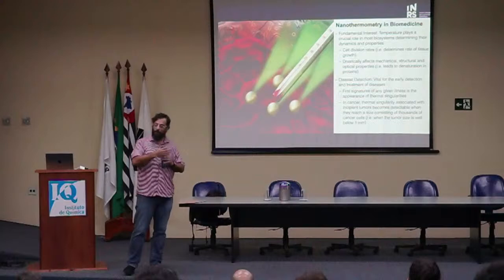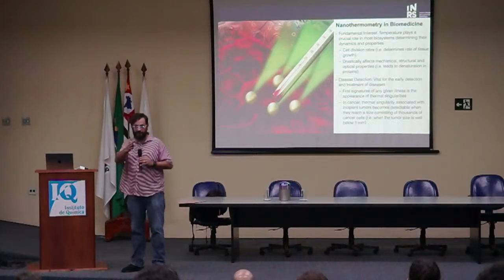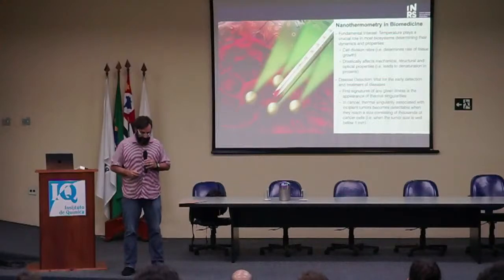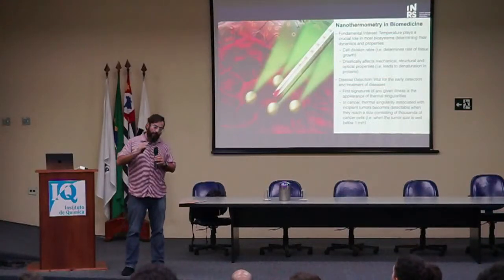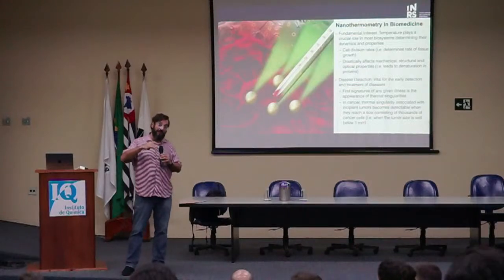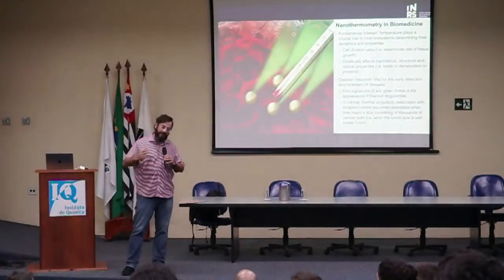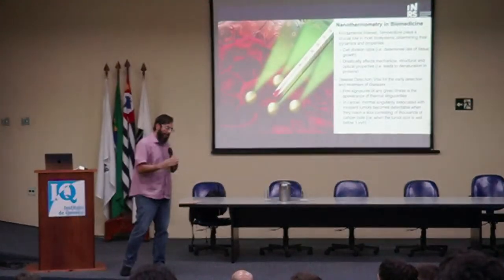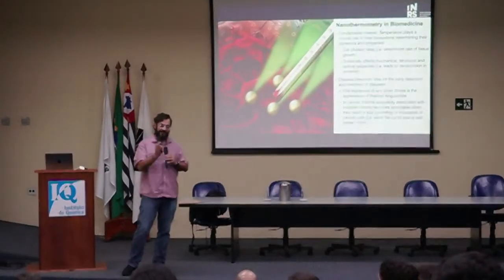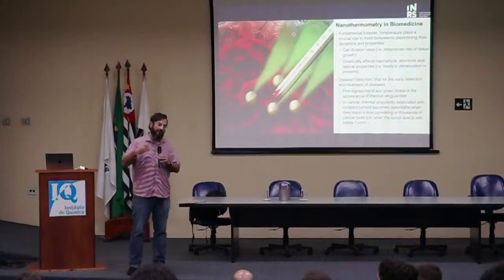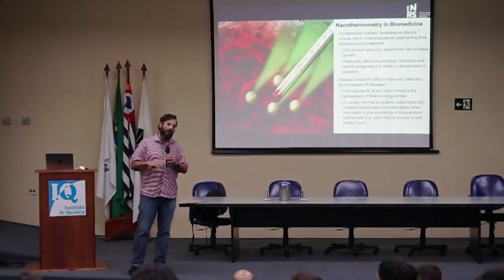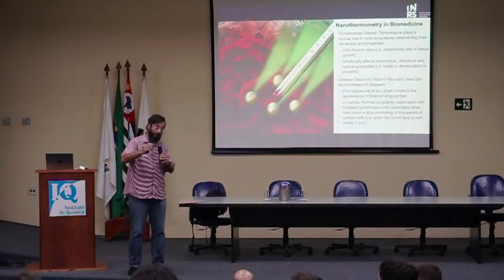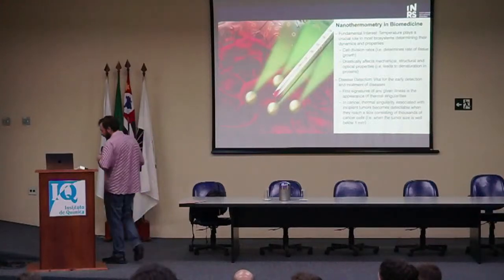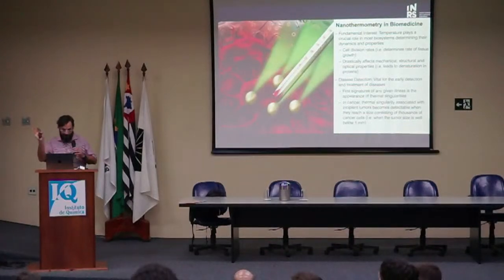We've done work with that. I'm not going to show it in this presentation, but I can show it if any of you have questions. But we've done work along those lines. And if you have a really good gold nanorod that has a very high heat conversion efficiency, it's so good at heating that when you excite the nanoparticles, you risk killing the healthy cells around, and then you start to get side effects that you don't want. So we thought, how about using thermometry in conjunction with photothermal therapy, where you can heat, and then in real time monitor temperature. So that's the preamble of why we were so excited about thermometry 10 years ago.